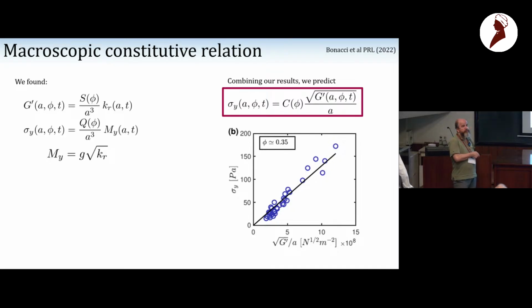This plot is already used by the cement industry. I'm a bit scared by that, but the idea that you have a relation parameterized by time between the shear modulus and the yield stress is something that did not exist, and now they are thinking about that. They find this square root law at the early age, and then they find something else. And so they are using it to characterize their system.